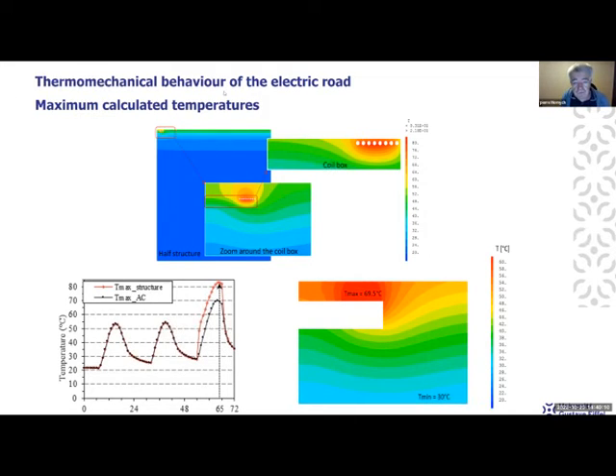So here is an example. We tried different scenarios, but here is an example of maximum calculated temperatures. You can see that the summer temperature generates temperatures in the top of the asphalt layers of about 50-55 degrees. And when you add the inductive charging, you can reach temperatures close to 70 degrees Celsius in the asphalt layer and even more in the coil block. So this means that in this scenario, in very hot summer conditions, you have temperatures which are exceeding the maximum temperature which could be allowed with a normal asphalt material.